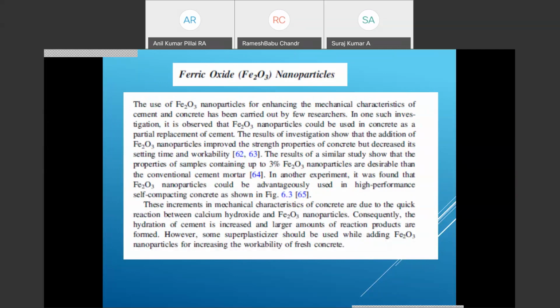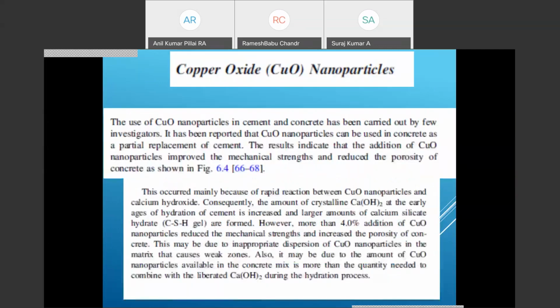Copper oxide: the crystalline copper oxide at early age of hydration of cement is increased, and larger amounts of calcium silicate hydrate gel are formed if you use copper oxide nanoparticles. However, more than 4% addition of copper oxide nanoparticles reduces the mechanical strength and increases the porosity of concrete. So you have to add copper oxide within a range of lesser than 4%. If it is more than 4%, it leads to a formation of pores and it reduces the mechanical strength.